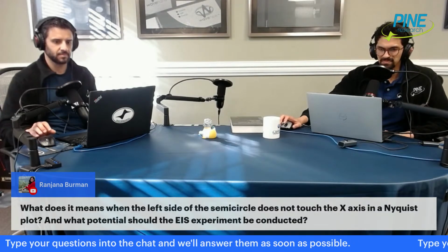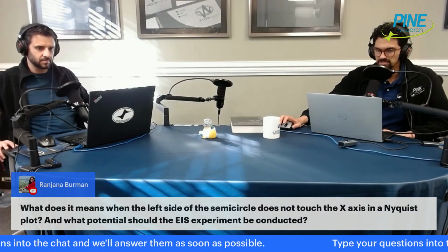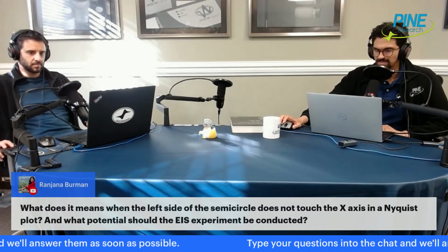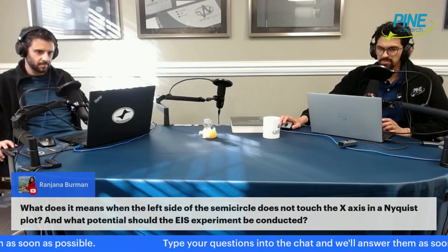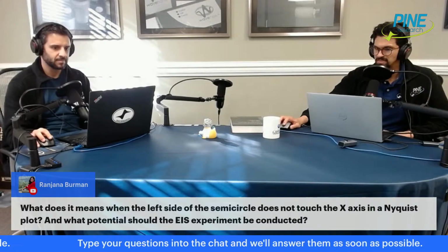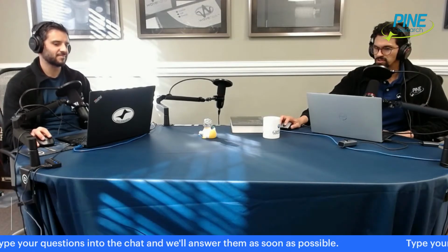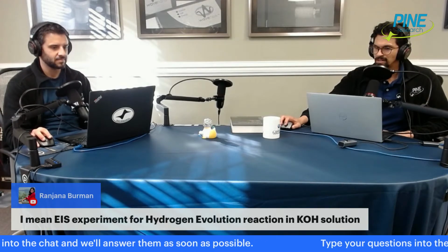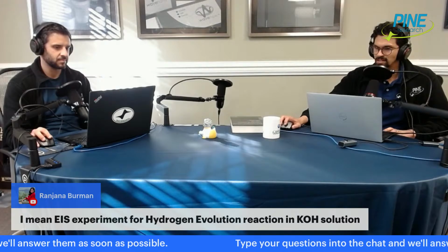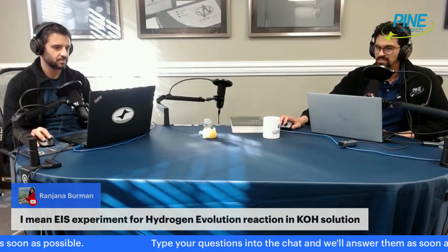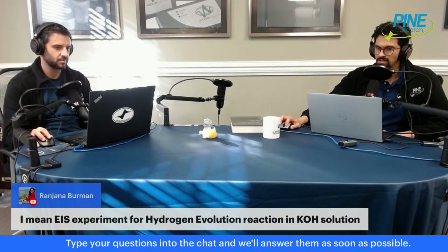What does it mean when the left side of the semicircle does not touch the x-axis in a Nyquist plot? And what potential should the EIS experiment be conducted at? She is referring to EIS, a hydrogen evolution reaction in a KOH solution.